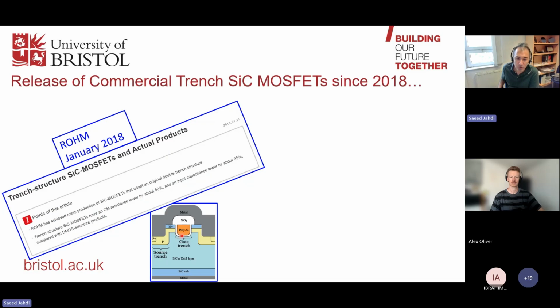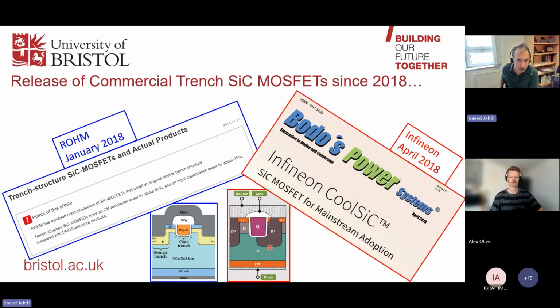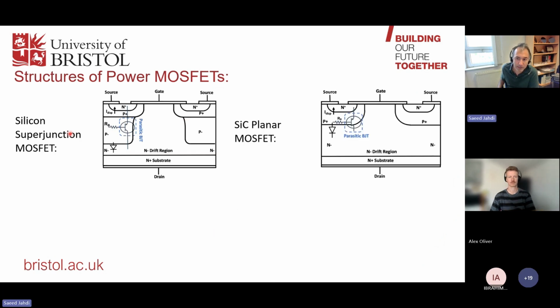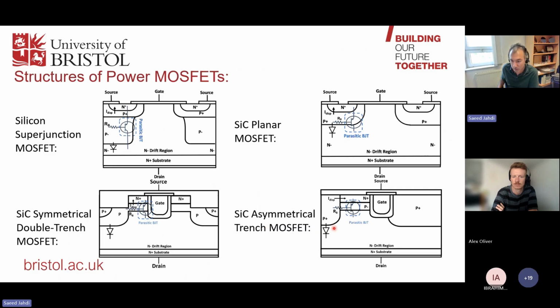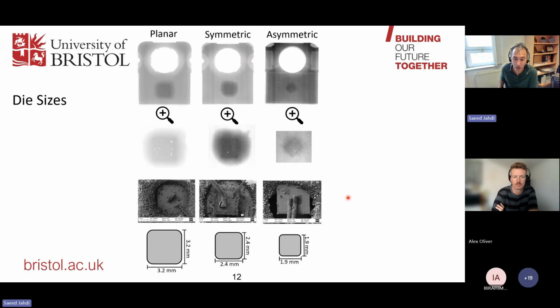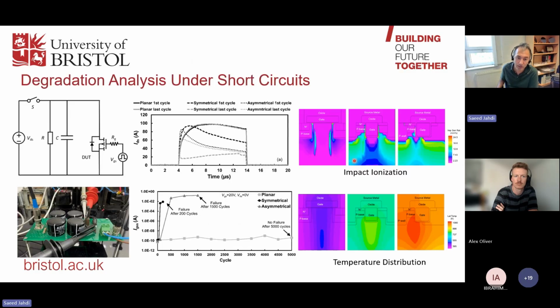This is what ROHM introduced, the double trench silicon carbide MOSFET. Infineon started with asymmetric single trench ones, and these change a lot of the understanding that we have had in terms of reliability of planar silicon carbide MOSFETs. There are super junction MOSFETs that are mainly made in silicon at this stage, and there are some prototypes in silicon carbide too. There are silicon carbide planar ones, the symmetrical double trench from ROHM, and the asymmetrical trench MOSFETs, again from Infineon. Each of these companies has developed their own patents and their own benchmarks in terms of performance, but the reliability of the devices also changes a lot with those changes. Also, the die structures are becoming smaller and smaller. The cell pitch in making the devices is becoming more aggressive, to increase the yield and reduce the cost, but that again has implications for the reliability.